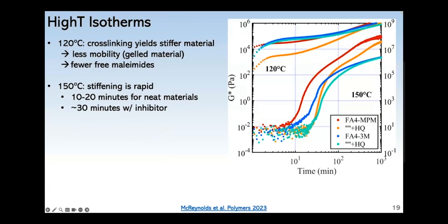Another way we looked at the maleimide self-reaction was to just isotherm at high temperature. So I picked 120 C plotted on the left and 150 C plotted on the right. So at 120 C, again, this is G star against time. At 120 C, the materials have already gelled, so they don't have as much mobility, for example, as the samples at 150 C, which show clear flowy behavior. But at 150 C, the neat materials show rapid stiffening after about 10 to 20 minutes. But with hydroquinone, that was delayed to about 30 minutes. What's interesting is at 120 C, even though the materials have already gelled, they gradually stiffen after a few hours, which is surprising since there's less mobility and there are fewer free maleimides.